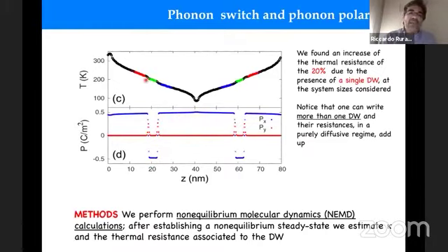Here, again, you have two small jumps in the temperature profile. What resistance associated to the domain walls do you expect? Well, if the domain walls were infinitely separate, the resistance would be twice as much as the resistance of one single domain wall. But if they are rather close, when phonons come, they will see a cluster defect.